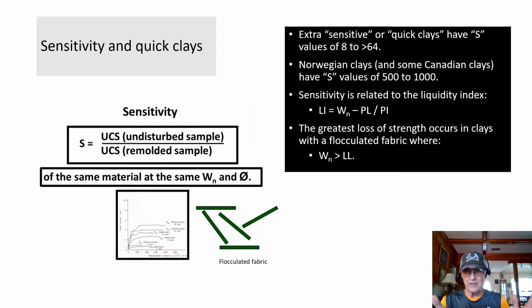Another important definition is the definition of sensitivity. Sensitivity is the ratio of the unconfined compressive strength of an undisturbed sample divided by the unconfined compressive strength of a remolded sample of the same material at the same water content and the same porosity. What we call an extra sensitive or a quick clay, those have sensitivity values of 8 to greater than 64. Now the problem is that some clays in Norway and some in Canada, by the way, have sensitivity values of 500 to 1000.